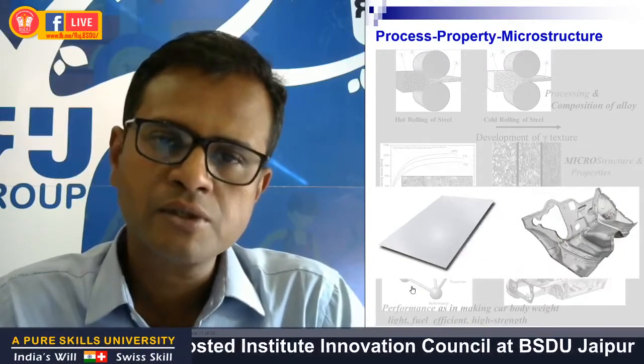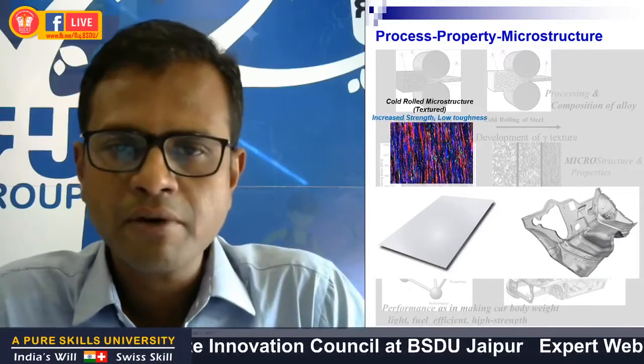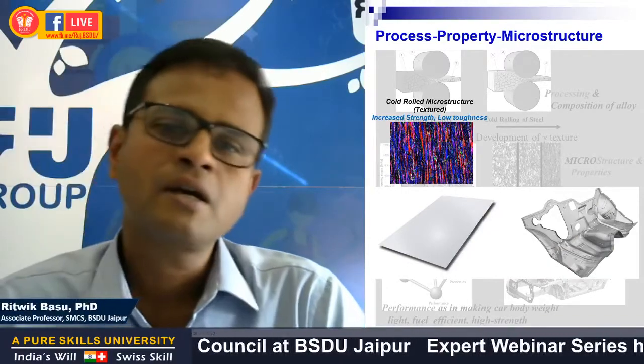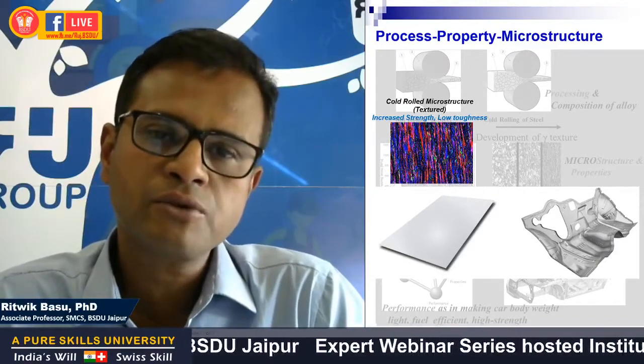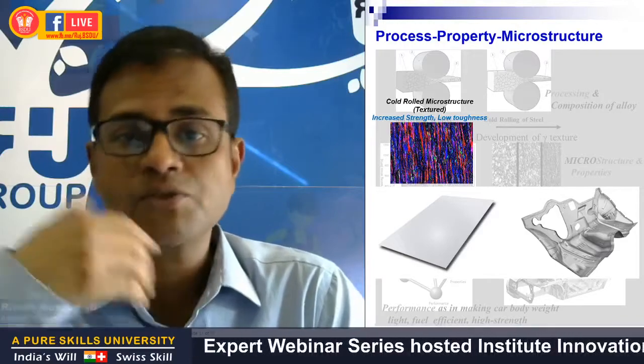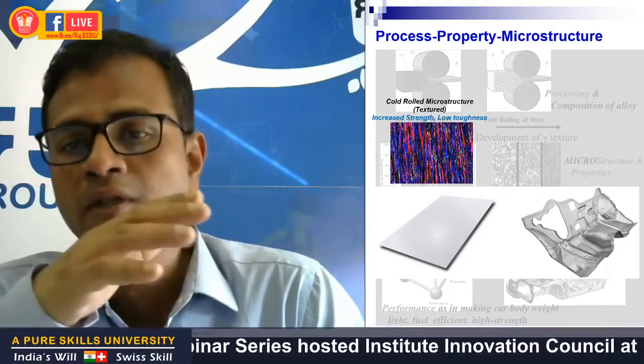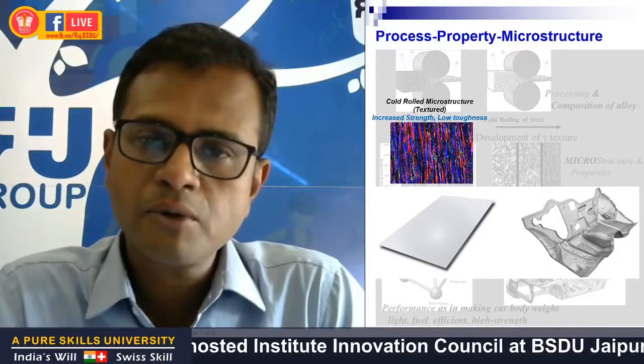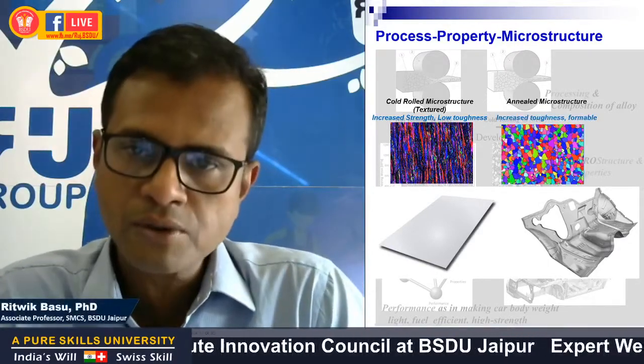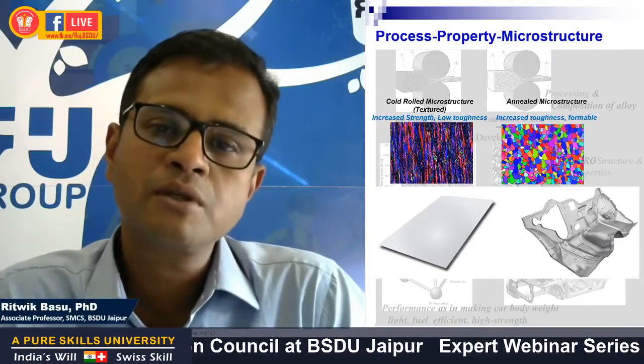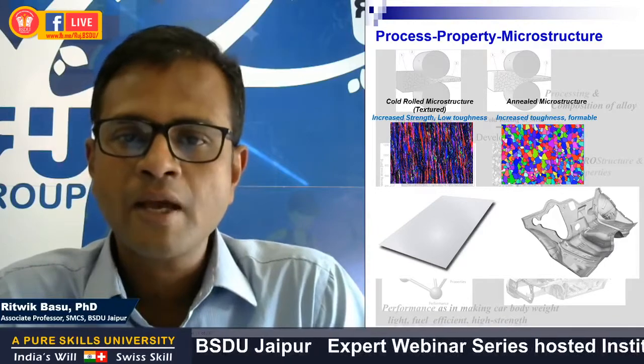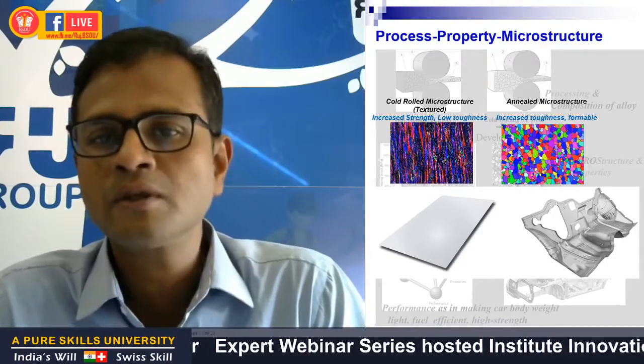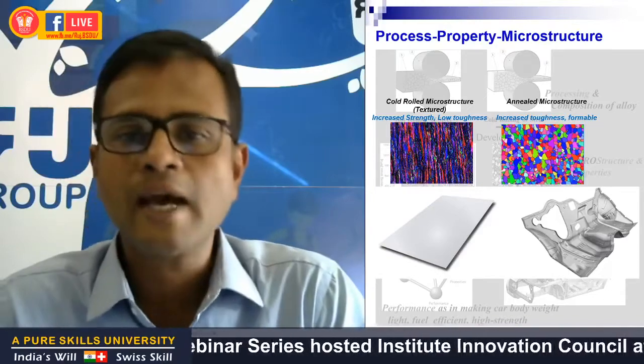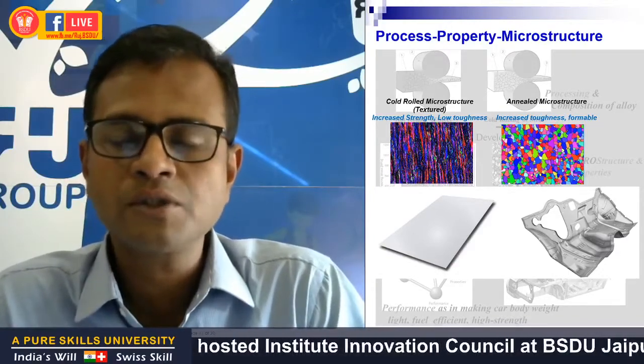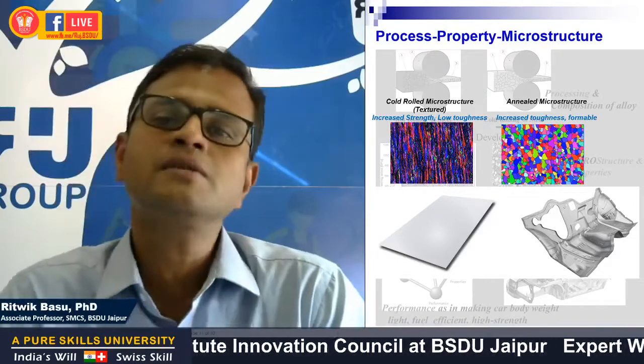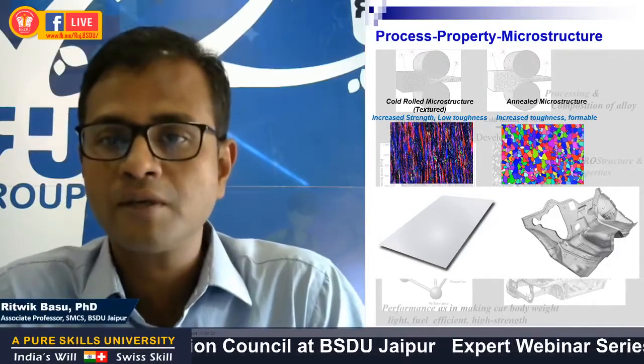So cold rolling, as I was discussing earlier, introduces significant grain refinement and texturing in the microstructure, and that results in high strain heterogeneity in the material. So the strength is seen to increase by several times, however the ductility drops. And interestingly, upon annealing, the grain refined microstructure is retained together with a nice distribution of fine equiaxed ferritic grains. And the strain that was induced largely during the cold deformation is also relaxed during the annealing stage, thus making the sheets softer. So the ductility of the material again increases. However, the strength drop is not so significant.